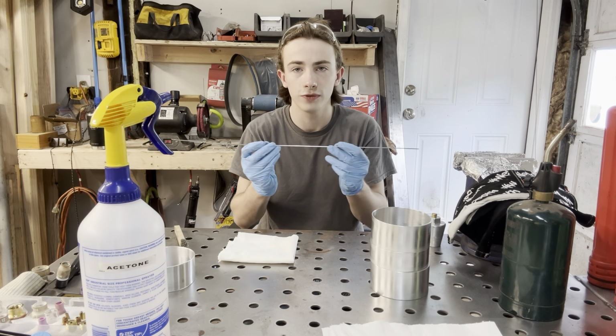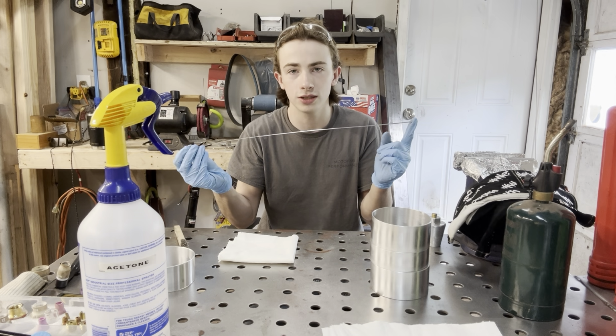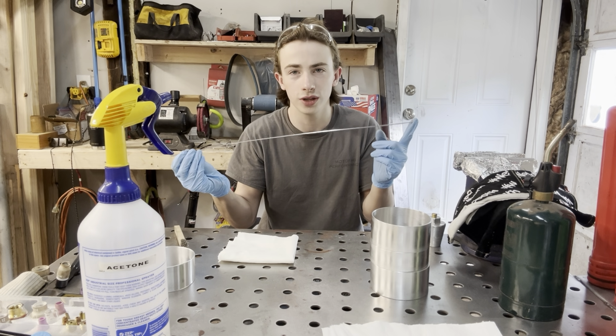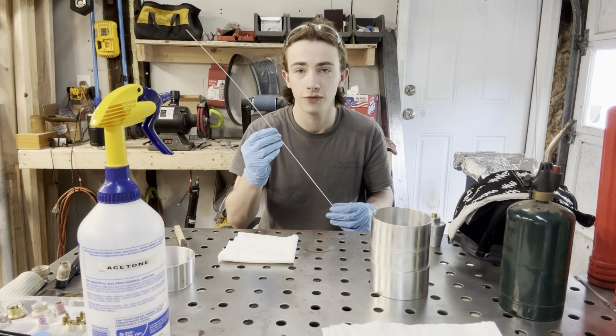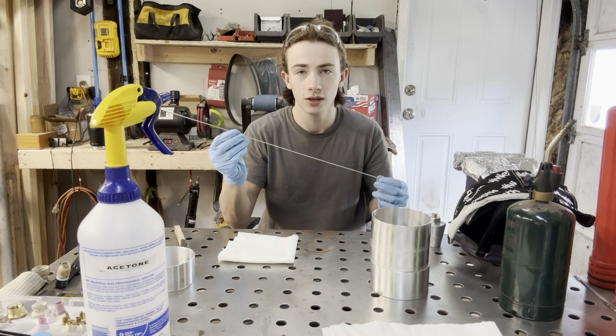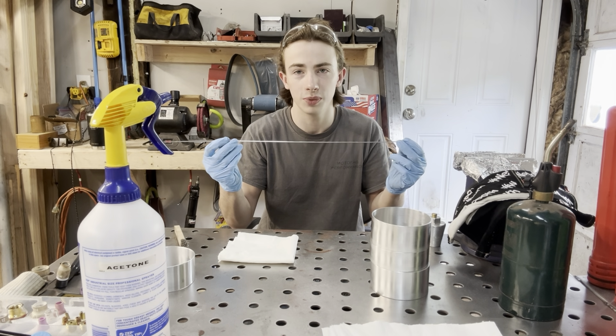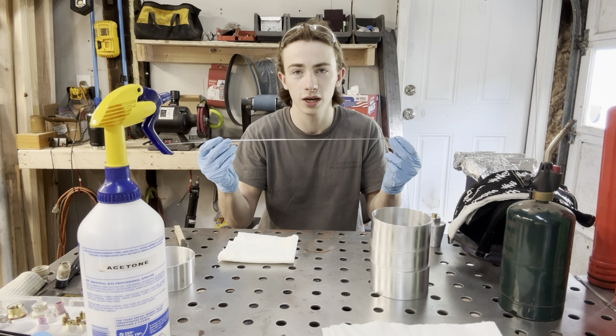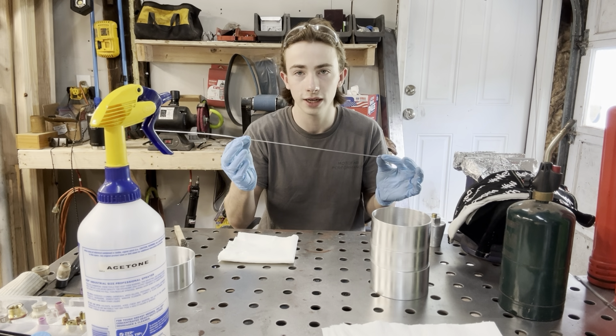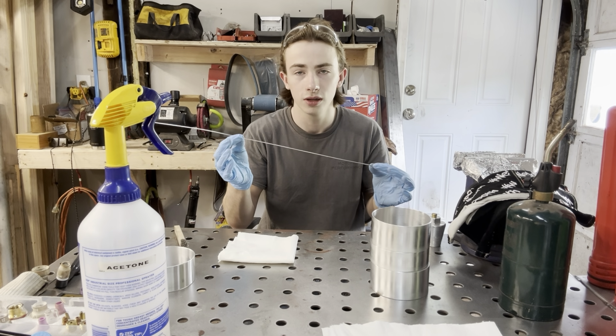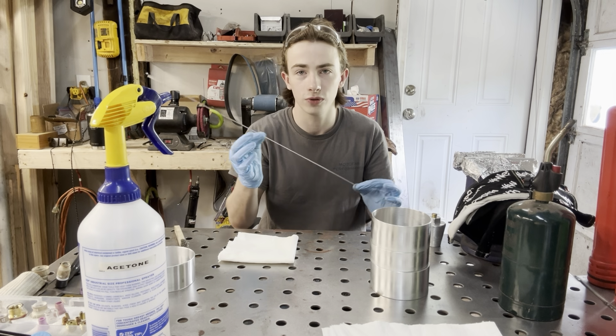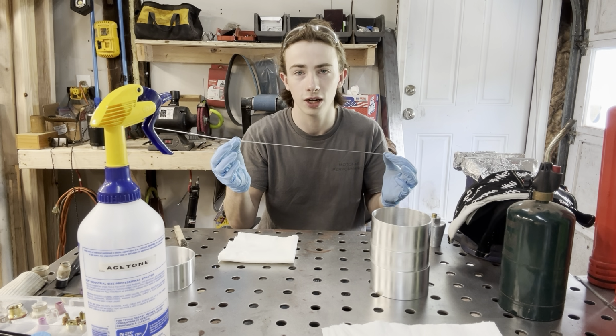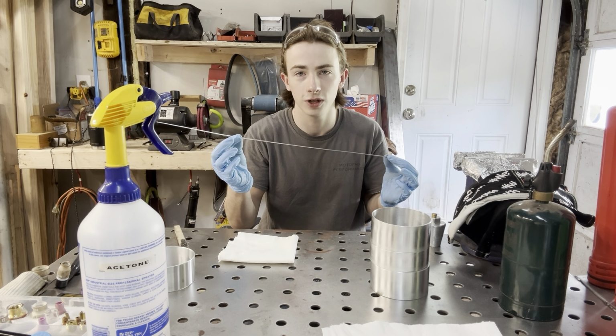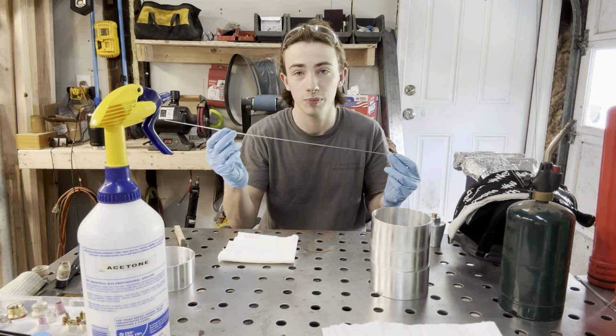My rule of thumb for aluminum filler rod size is to use one size larger than your material thickness, which is a difference from steel and stainless, where the rule would be typically to use one size smaller than your material thickness. Aluminum does like to have a good bit more filler, which is also helpful for keeping it cool and preventing cracking. If you don't have enough filler, it is very prone to cracking.